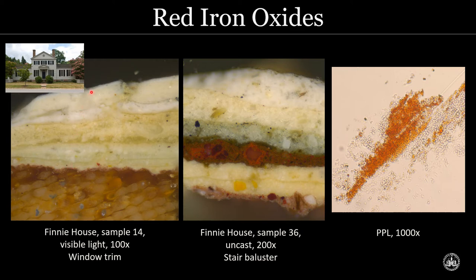Here are all of the paint layers applied over time, and I'm actually not showing the entire sample. These are just the earliest layers. But there is a very thin red iron oxide primer applied to that wood. So you can see how thin the primer was compared to the other paints. And I found this very similar early stratigraphy everywhere throughout the entire house.